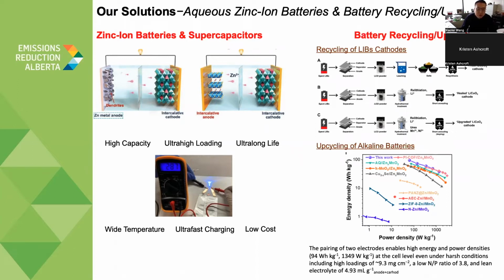And the batteries that we fabricate in the lab can provide very high loading. Typically, we can realize a mass loading over 50 milligrams per centimeter square, which is much higher than that of typical lithium batteries, for example, only 2 to 10 milligrams per centimeter square. Also these batteries can provide ultra long life, cycled for over 1 million cycles. And of course, given the materials and our unique design, we can also realize these battery applications in a wide temperature range from -60 to room temperature or even higher, to 60 degrees C.